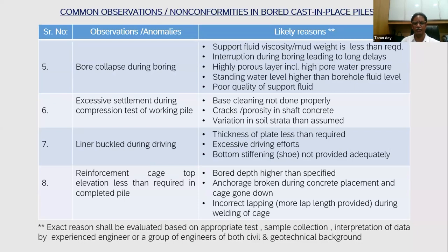If the anchorage gets broken, the cage may go down. Incorrect lapping. If you put more lappings, the total length of the cage is likely to be smaller than the actual. So the top goes down. So these are the likely reasons. For the exact analysis of the reason, you need to have the sampling, additional investigations, the analysis of the data, sometimes alone or sometimes in a group, to find out the exact reason so that the repetitions can be stopped.